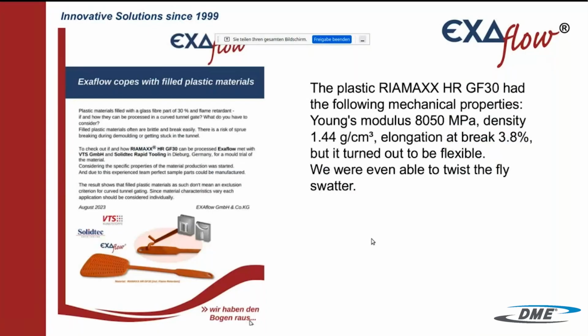Three years ago, a customer from Italy had some projects, many molds, I guess 12 different molds, 12 different plastic parts for the electro car, Tesla and so on industry. The plastic was a RIAMAXX with 30% glass fiber and also a powder ingredient so that it cannot burn. And from the specs of the plastic, the mechanical properties, we thought it cannot work. But then we did a test.